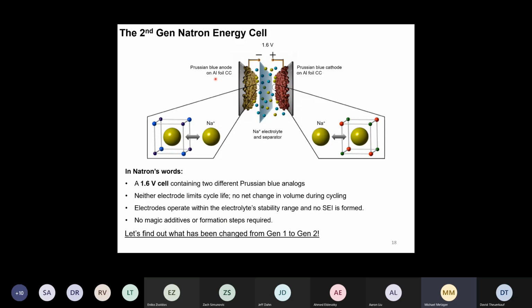Okay, so let's look closer at their cells. So again, we have 2 aluminum current collectors and 2 different Prussian blue analogs coated on those. And then they put this together again in a sodium containing electrolyte with a separator. And now they get a 1.6 volt cell. So obviously they changed something to their electrodes. So here they only draw these sketches of the crystal structure of the Prussian blue analogs. But let's look a little bit more closely as to what changed from generation 1 to generation 2 here.